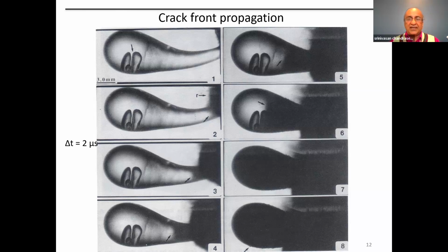But remember, fracture is not propagating in air, it's propagating in a solid. Typically cracks move in solids with a peak speed of about 35 to 40% of the velocity of sound in the medium. So in glass, a crack would propagate at a peak speed of about 1,700 meters per second, and the sound velocity in glass is 4,500 meters per second.